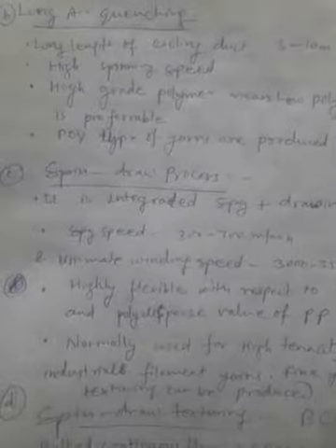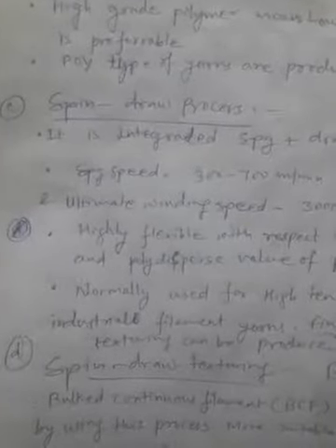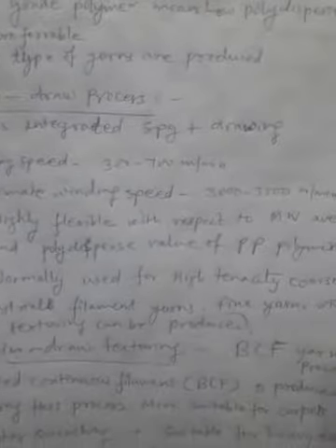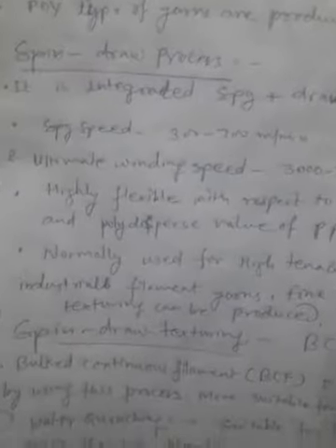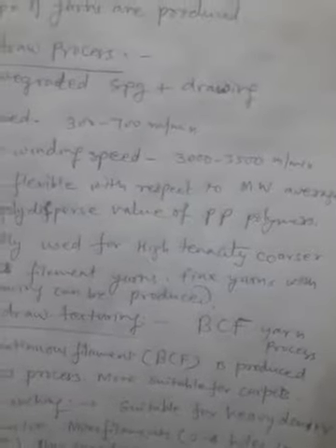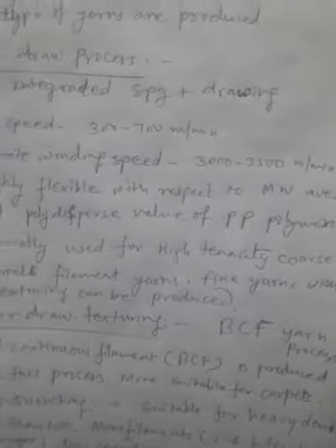Partially oriented yarns, meaning POY type yarns, are produced in this. Now another process, the spin draw process, is an integrated process. You can say the spinning and drawing are both carried out simultaneously. Spinning speed is kept at 300 to 700 meters per minute, and the ultimate winding speed is kept much higher, that is 3000 to 3500, meaning 7 to 10 times stretching can be imparted during this process.